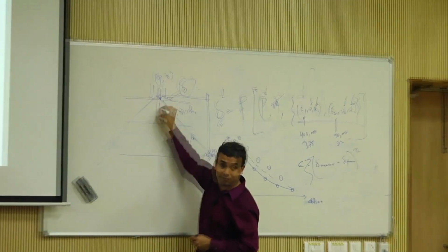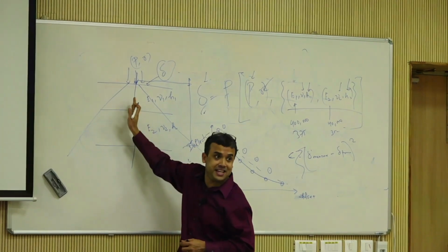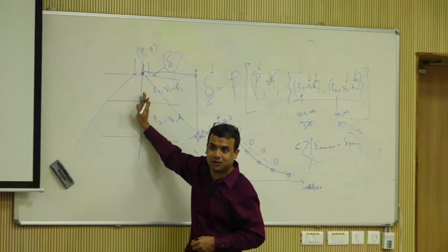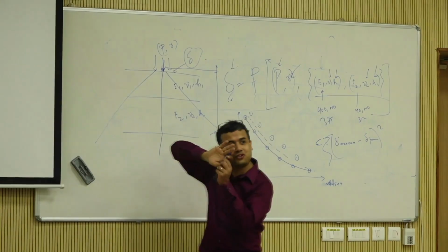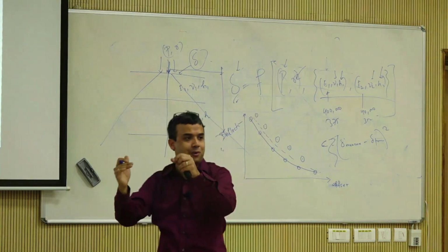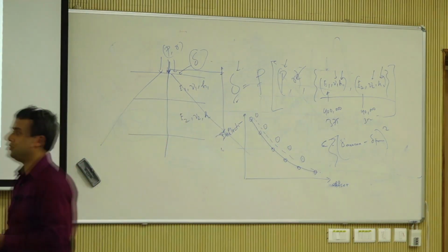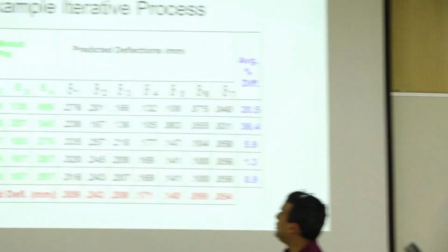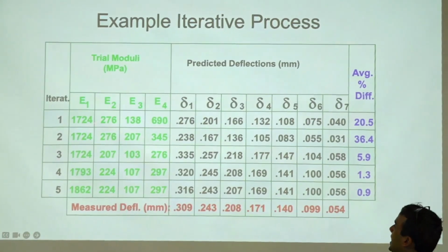what layers affect your properties? All of them. So if you want to match D0 to start with, you're going to be chasing your tail, right? So you have to start from away, only change E4, then only change E3, then go back to E2 and stop. Start from the outside, makes life easier. So that's the reason from iteration 1 to 2, you don't see any E1, E2 change.